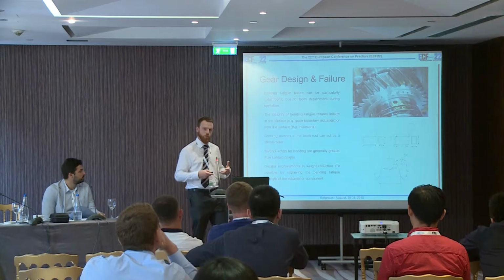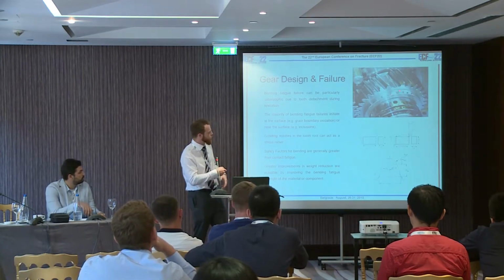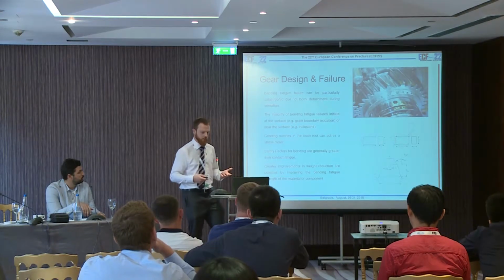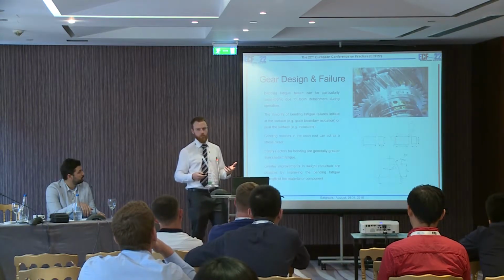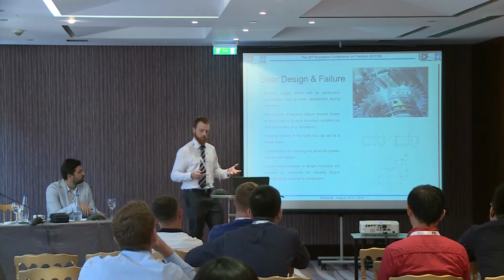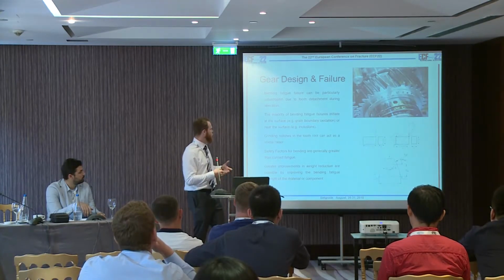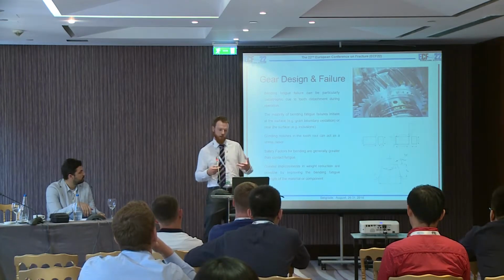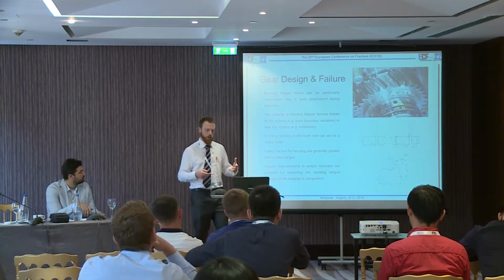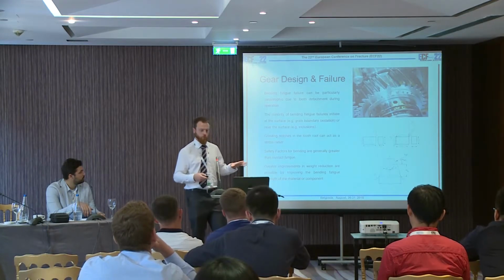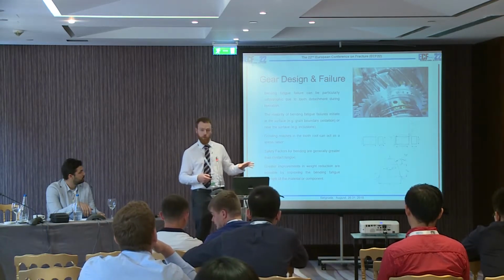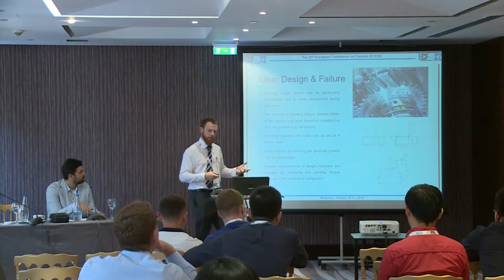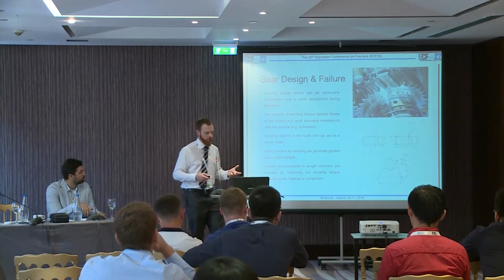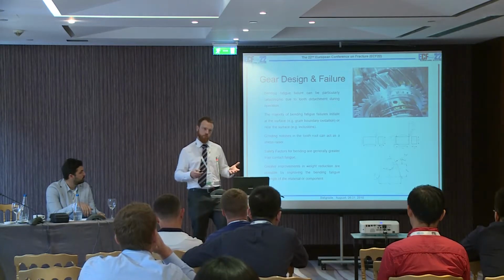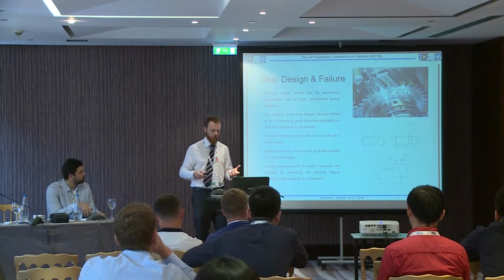So bending fatigue can be particularly catastrophic because you can get complete tooth detachment. That tooth is going to have to go somewhere, and typically that's going to go into the gear mesh, or it's going to go into associated drivetrain components such as bearings, which is very bad. The majority of bending failures initiate at the surface, for example at grain boundary oxidation, which is a problem that we see in gas carburized gears, or it might be near surface from inclusions from the steel making process. It can also be from geometric features such as grinding notches, but we do try to avoid those through manufacture.